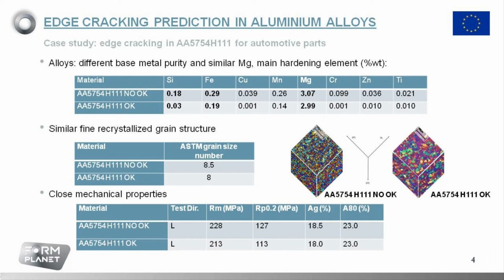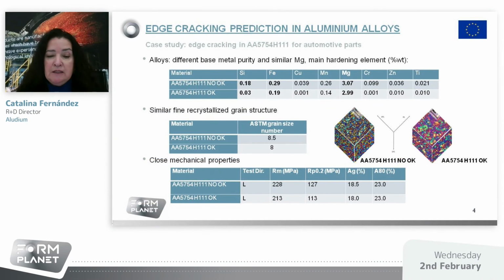In the trial material regarding chemical composition, the main hardening element, the magnesium in this alloy, was kept at the same level, but the amount of iron and silicon, the main impurities, was reduced. Both materials present a fine recrystallized grain structure, ASTM number 8 and 8.5, quite similar. But as a consequence of its higher purity, the new material shows a slightly coarser grain size, detrimental for the stamping process. Regarding the tensile test, the results are quite similar. Also, we can conclude in this first part that the standard metallurgical studies are not able to predict the edge cracking.